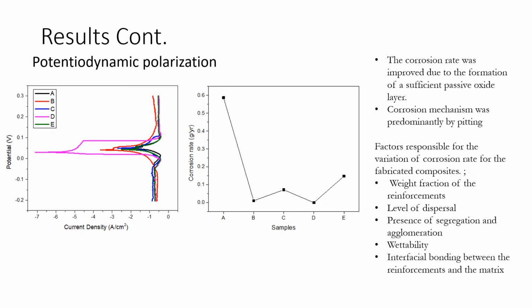As seen in the figure, the corrosion resistance of the reinforced samples was way better than that of the base metal. Albeit the case, it was also seen that there was no direct pattern in terms of improved corrosion resistance for the reinforced samples, and factors that could be responsible for this include the weight fraction of the reinforcement, the level of dispersal, the presence of segregation and agglomeration, wettability, and interfacial bonding between the matrix and the reinforcement.